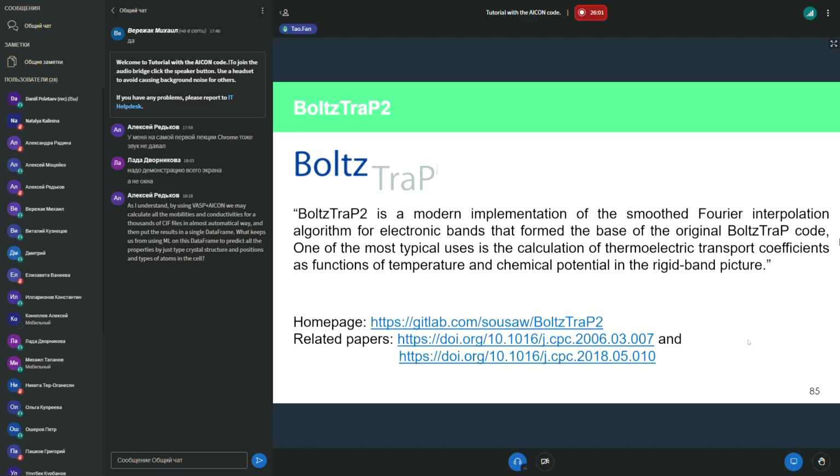This, however, will cause a problem for some results of BoltzTraP, such as the electrical conductivity or the electronic thermal conductivity. They are actually not the direct results we want, because their data include the relaxation time implicitly. That's why BoltzTraP calculation is much faster, but it also means that users need to get this electronic relaxation time from other methods.